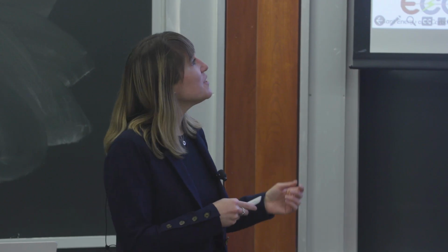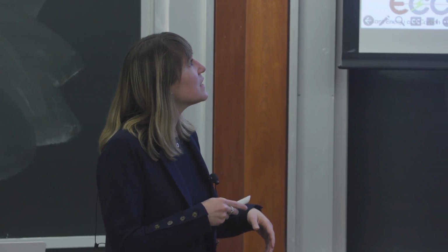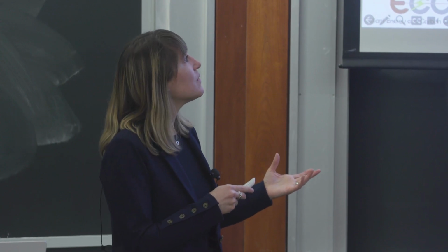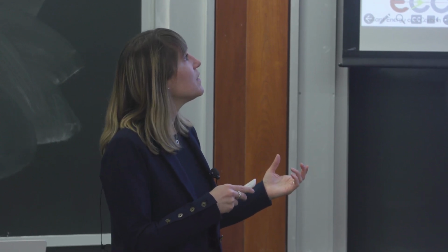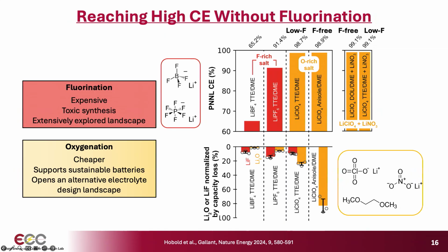And just to make the point, we took a high-performance electrolyte that used the FSI anion, which has fluorine, and we replaced it with either lithium BF4 or PF6 anions, so fully fluorinated anions, changing nothing else, and the capacity actually decreased quite a lot. So in other words, fluorination is really not a unique path to high Coulombic efficiency, and in fact, you don't always necessarily see fluorination translate to high performance.